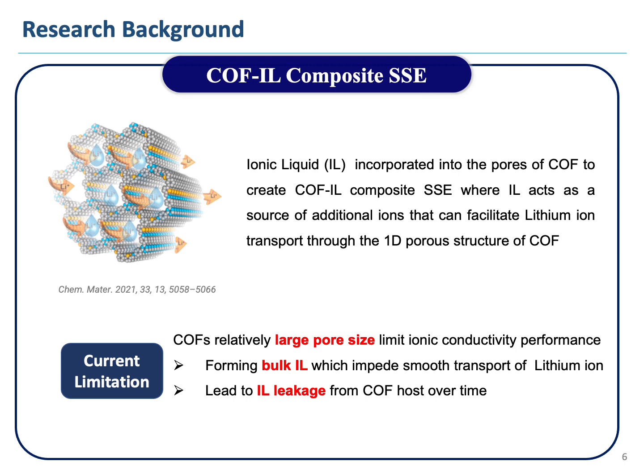However, the relatively large pore size of COF will cause confined IL forming bulk structure, which can impede the smooth transport of ionic liquid and lead to leakage over time. Thus, for the use of COF-IL in practical battery application, performance of COF-IL composite materials as solid-state electrolyte must be enhanced by introducing a pore modification strategy that allows the control of pore size for efficient ionic liquid transport while preventing ionic liquid leaching from the host material.